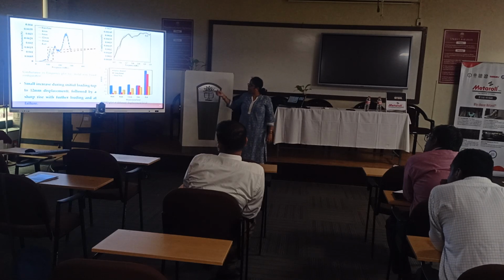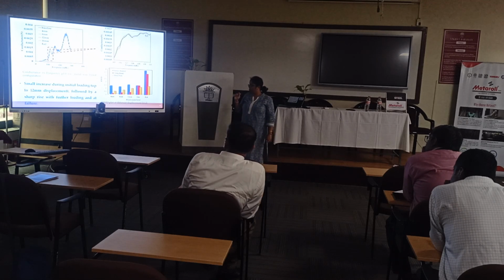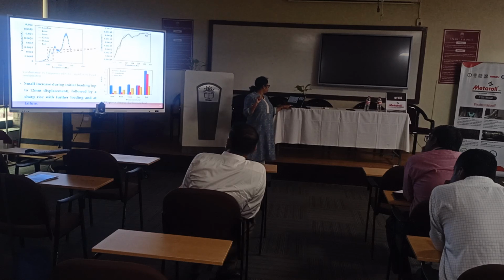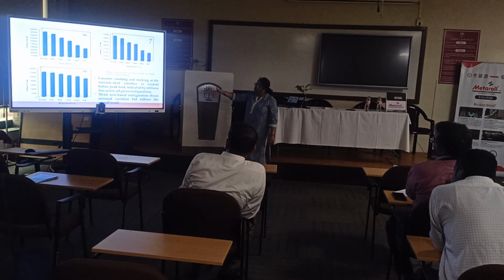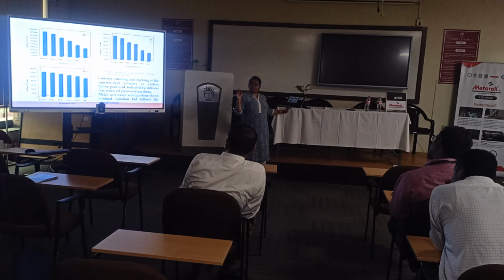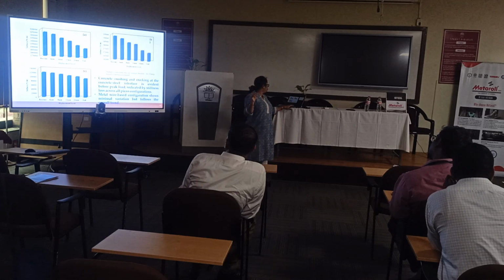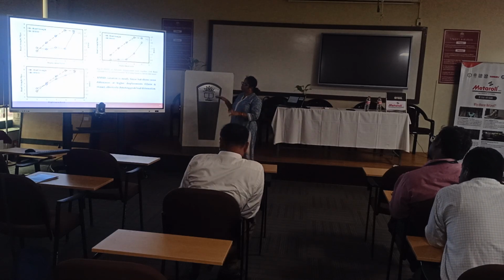The failure mechanism is shown very well. At least the clamp test and the metal wire test are good enough to see the changes through their sensing capacity, which is encouraging. Similarly, we see the stiffness behavior. The stiffness from different baselines to the failure is decreasing more, which gives the indication that the damage that has happened is well controlled, or well captured, through the sensor reading. Now, we also do some RMSD variation based on the bond strength improvement.